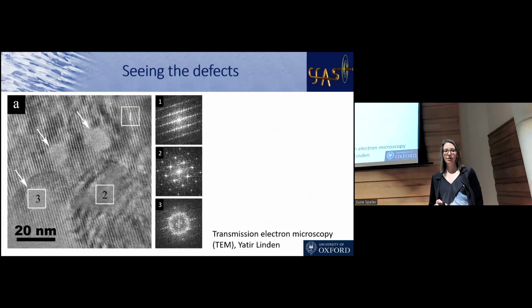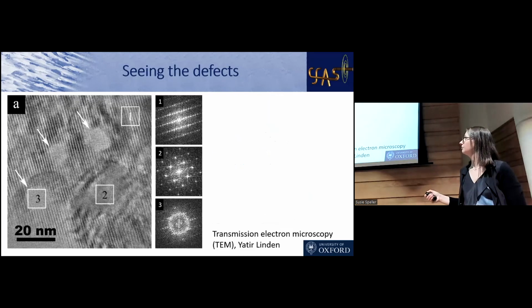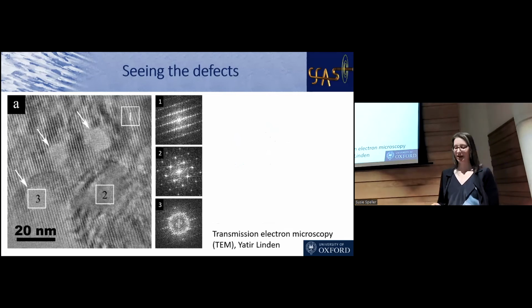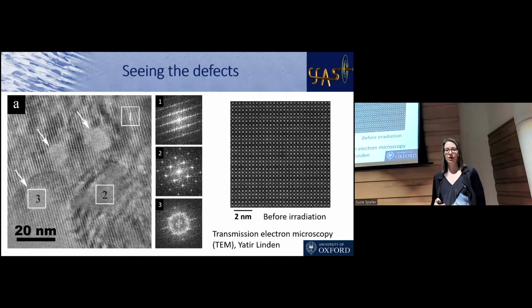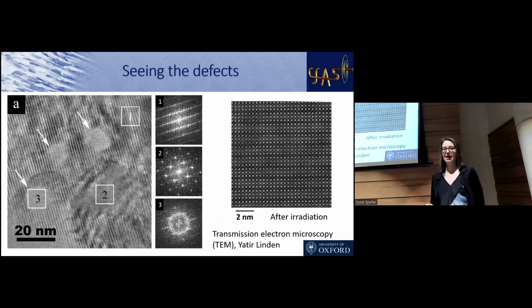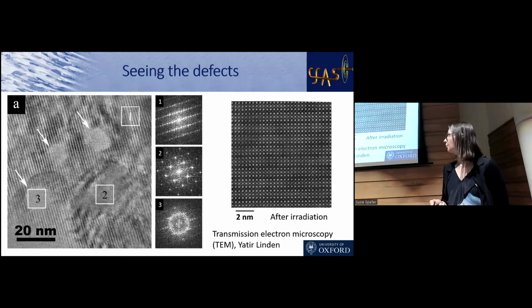And if we have a little look at what it looks like inside the material, you can see that you get these regions. These are the crystal planes, and you can see you get these regions that are damaged. Okay. And there are lots of things we've been working on to look at what kind of damage we're doing in between those defects. So you can look at the perfect material before you irradiate it. You can look at it after you irradiate it, and actually most of the atoms are still where they should be. So we've been doing a lot of work to try to find out what it is that's going on in the material that's making the properties get worse.